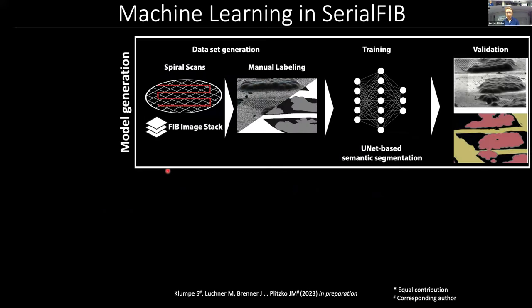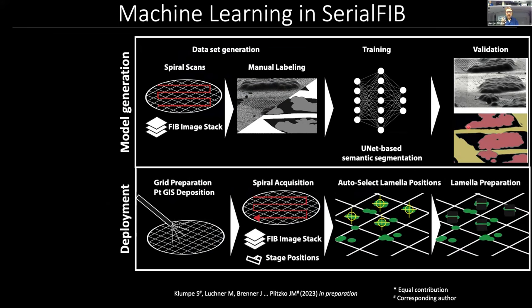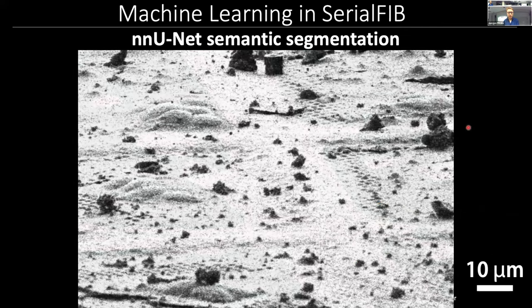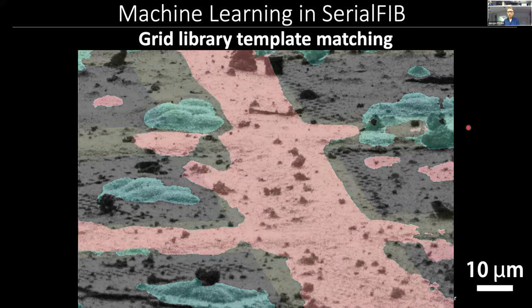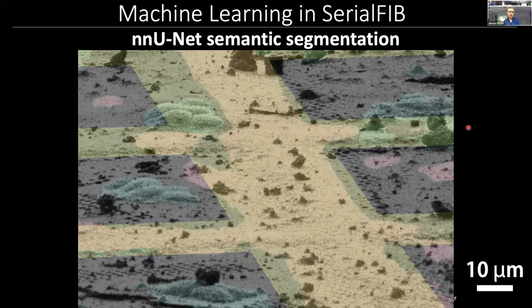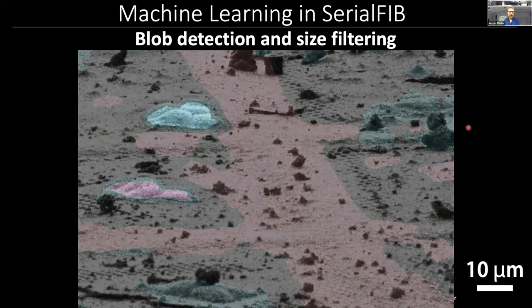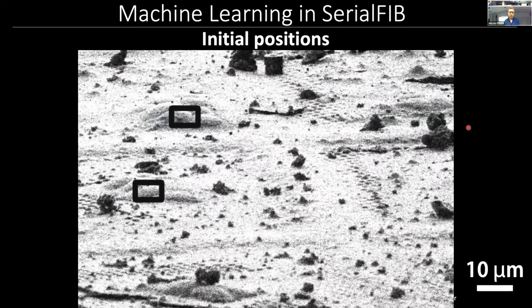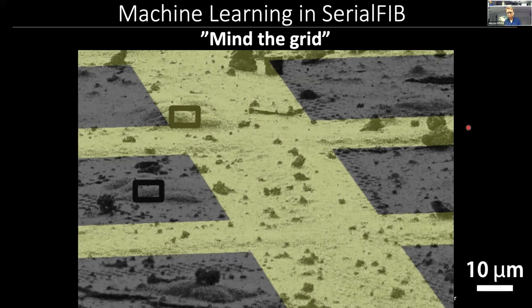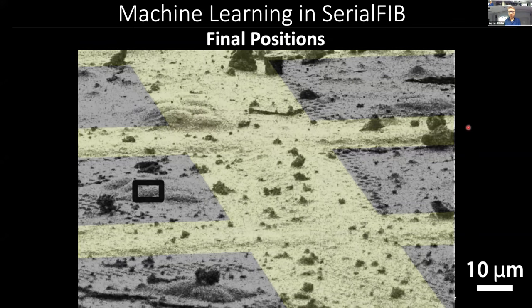And one of these endeavors is machine learning in cryo-FIB. So what we did was to take FIB images that we segmented manually and trained a U-Net model to do segmentation of the grid bars as well as cellular material. And then on the microscope, on the fly, we can use those models to guide lamella preparation without any user intervention. So we have our original image. We get this U-Net segmentation from that image. We can use a grid library to find out the orientation of the grid bars. We can then use the cellular segmentation to find instances where we would have enough cells to support a lamella. We choose positions based on this, shown as little black squares. And then finally, filter those against the grid bar segmentation to get our final lamella positions.